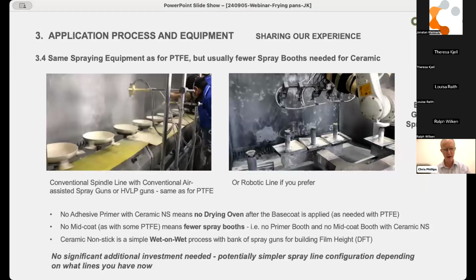Spray equipment, exactly the same. So you can use your existing spray guns, your existing spray booths. Ceramic non-stick is slightly simpler here because you're applying the first layer and the second layer wet on wet. It's just film height building within the same spray booth. Whereas PTFE, you'll need a separate booth for the primer, then a drying oven, and then depending if you have a mid and a top coat, you'll have another 2 spray booths as well. But you can use all of your existing equipment if you have a spray line that can apply PTFE. Next slide.